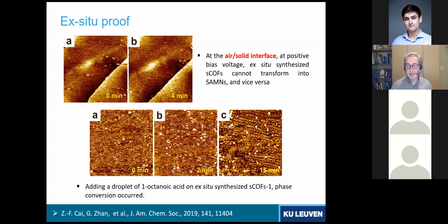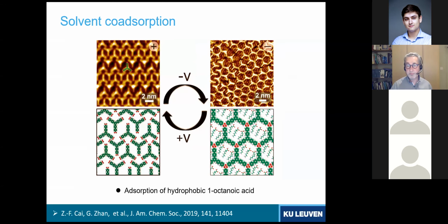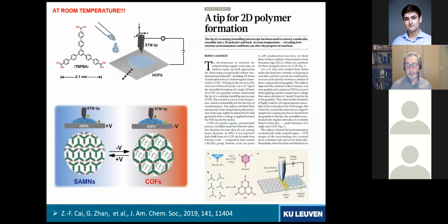Indeed, if we add octanoic acid to a dry film and then do the bias switching, then we can induce these dynamics again. I think that's a powerful approach to investigate chemical reactions on surfaces, such as depolymerization reactions. This is one of the things we are doing right now. A recent example is that we have not only looked at monocomponent systems, but we also started to look at multi-component systems as far as 2D COF formation is concerned, again based on the control of the STM-related electric field that we can apply.